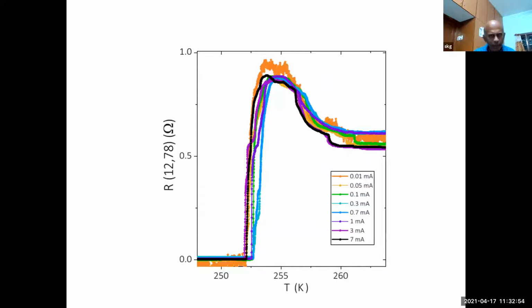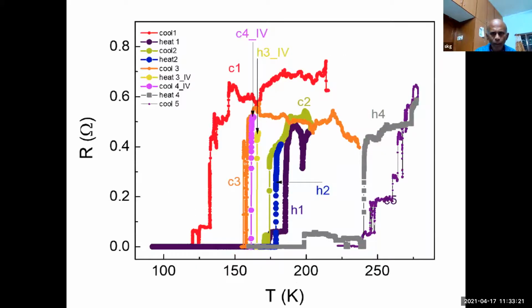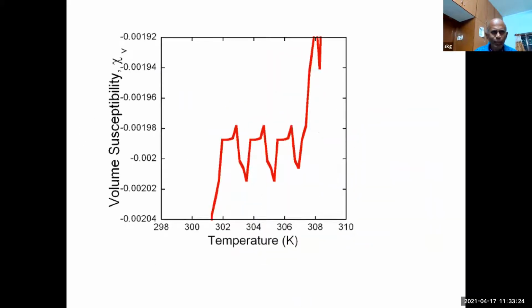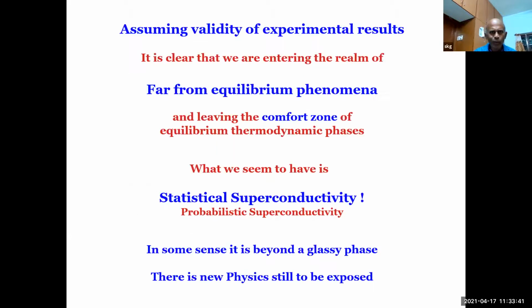And also, this is another very beautiful result in the last paper. What they see is a resistance maximum before the resistance plunges down. This is characteristic of nanograins of regular superconductors, where there are pi junctions and these pi fluxes in nanowires and so on. So it looks almost like that. So it comforts them. So there is something like that going on. Then you look at this volume susceptibility, diamagnetism. It starts falling at 308 degrees Kelvin. It's like room temperature in Chennai soon, because we'll hit 43 degrees Celsius very soon with high humidity. And then it drops and goes up and drops and so on. So what's going on?